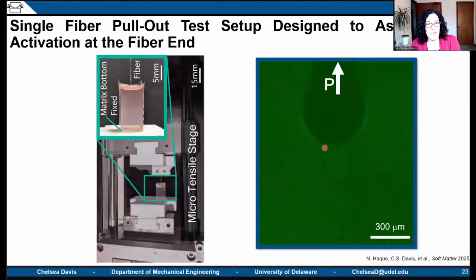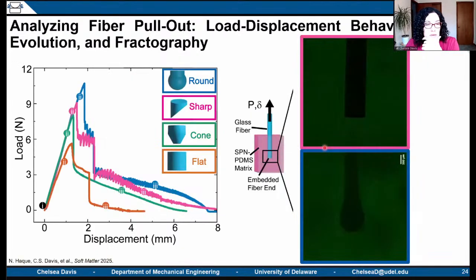So this is a round fiber geometry, and we can go through and characterize the load and displacement relationship of all of these. For the 4 different sample geometries that we utilized, we see a fairly systematic difference in where the fiber end starts to fail or pull out of the matrix. And we see two very distinct behaviors. Between the round and the sharp, we see some distinct stick-slip sliding events. But for the cone and the flat, we saw much smoother curves, and we also saw separation at lower forces.